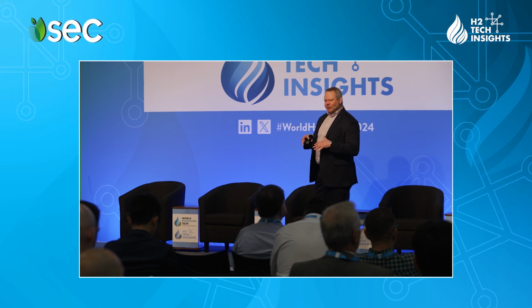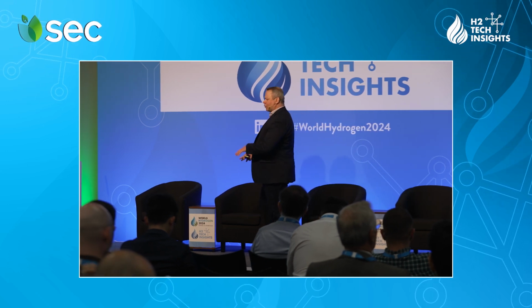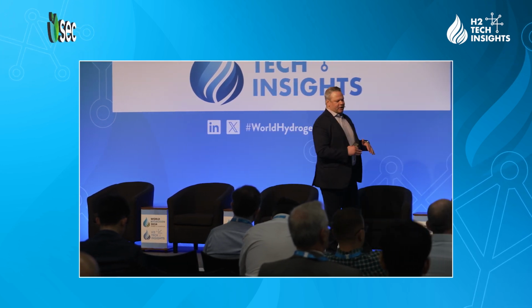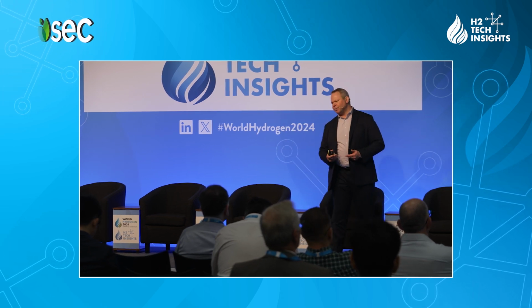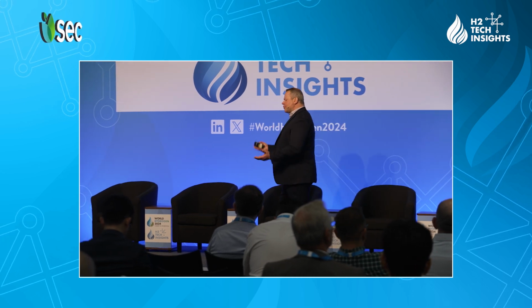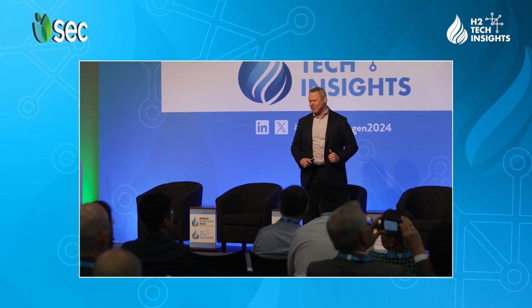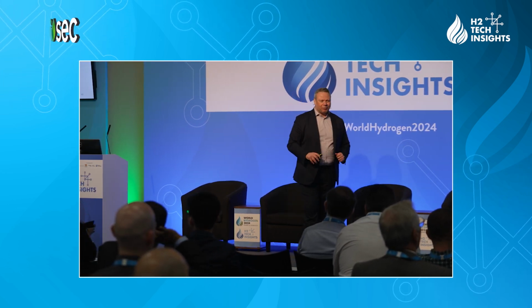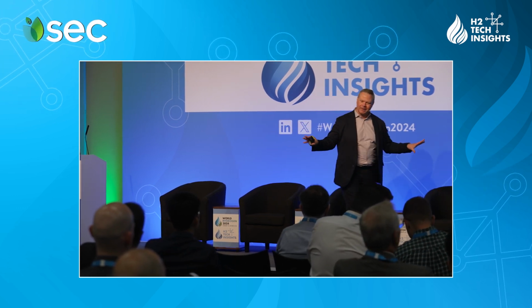So we've started to actually study the fundamental functional relationship between porosity and performance when the loadings get low. And I think this is a fairly new learning that the US national labs and the academic groups in Europe are starting to get wise to. But the reason that it's new is because it's been obscured in the past. Because loadings in the past were 1, 2 milligrams per centimeter squared. You can still buy commercial CCMs at 3 milligrams per square centimeter. If you use 3 milligrams per square centimeter, you could put a chain link fence down as your PTL and the performance would still be fine, okay?